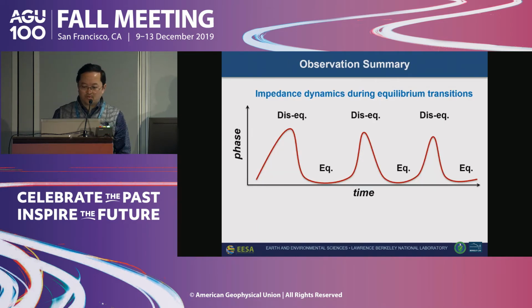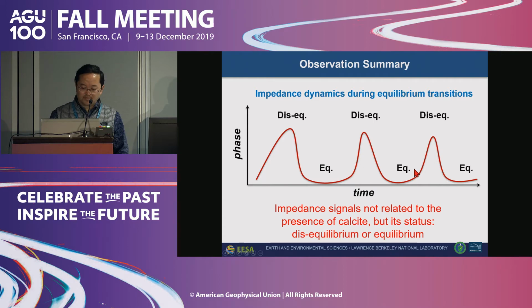So just to summarize what we are thinking, what's really happening is this cartoon: when you look at time versus the signal, when you transition into disequilibrium, you have this increase of the signal. When you fall back to equilibrium, you have this decrease. This is the pattern we're observing in the experiment, which suggests the signal we're observing is not related to the presence of calcite, but rather its status, whether it's under equilibrium or disequilibrium condition. So this is very interesting, and the question is why.